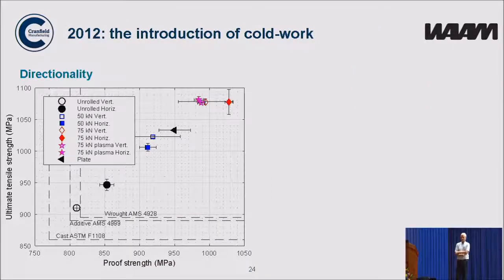So this is a plot of the proof strength against the ultimate tensile strength. The 2 points in the bottom left-hand corner are the as-deposited material in different directions. The 2 blue points are with 50 kilonewtons of rolling load. The triangle is the wrought material that's currently used and was tested for comparison. And then at the top right, you can see with a 75 kilonewton load, we have very high strength, about 1080, and we have a proof strength of about 980.